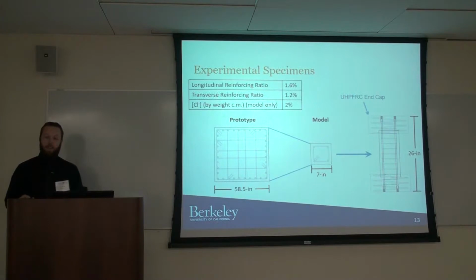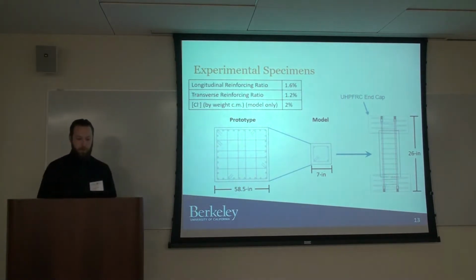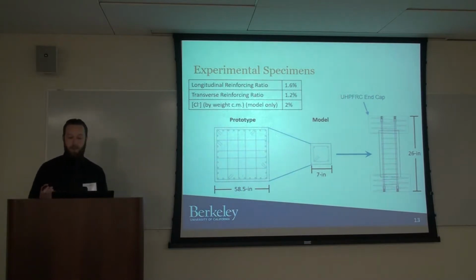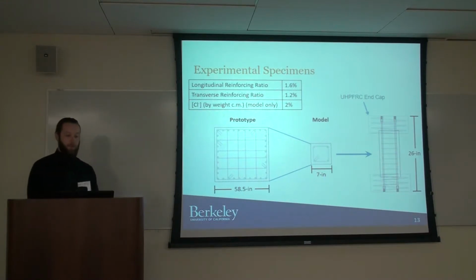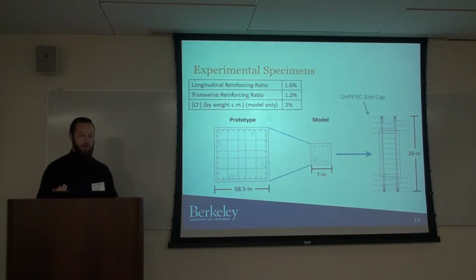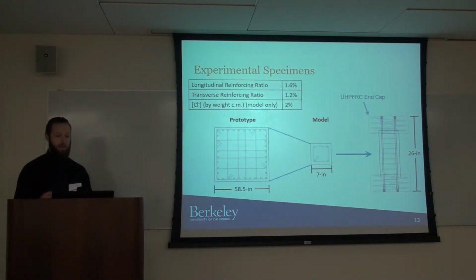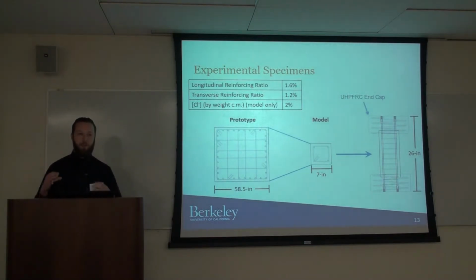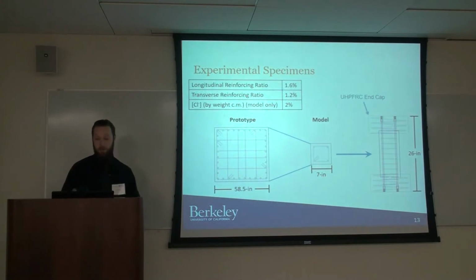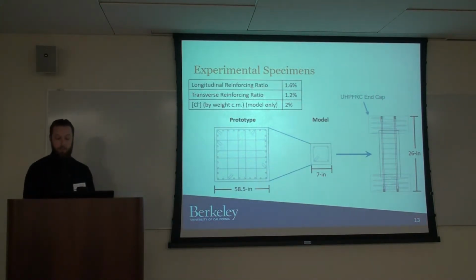And a closer look at our test specimen. We have scaled down with a linear scale factor of around 8, so 8.37, and we've taken a prototype column, and scaled it down to be more physically manageable. And so we have a 26-inch section with reinforcing ratios shown here, and we've cast some high-performance concrete end caps to make sure that our boundaries remain elastic and don't contribute to damage that we're seeing when we're conducting the test.